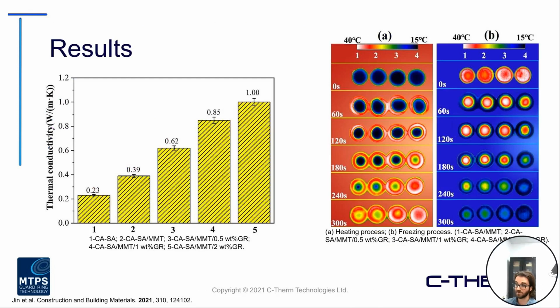Then we look at some of the results that were obtained. First, on the left here, thermal conductivity. As was somewhat expected, as you introduce new components, even just going from 1 to 2, where 1 was just your base PCM and 2 is noted by the introduction of the MMT substrate, MMT did show a marked increase in the conductivity measurement. Then the following 3, 4, and 5 are continual increases in the amount of graphene that was added. As would be expected, you can see this clear trend of increasing thermal conductivity.